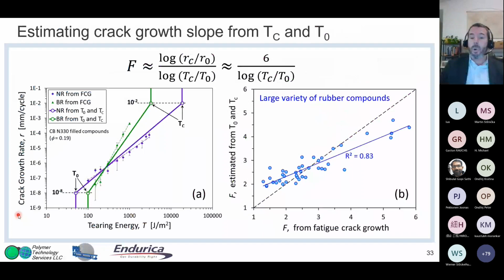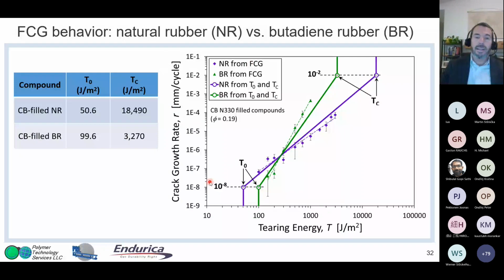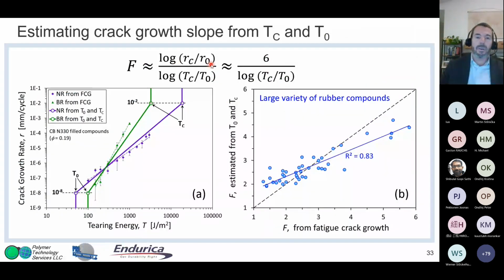So we showed that this actually works pretty well for a large variety of rubber compounds. If you get a crack growth slope F from fatigue crack growth testing, and then you get a value of F estimated from T0 and TC. Remember, I told you we can assume 6 decades, right? So here's 10 to the minus 2, here's 10 to the minus 8. That is 6 decades. So that's where that 6 comes from. It comes from RC over R0. And then if you take log of TC over T0 on the bottom, you can get a measure of F, right? It's just this over this. And when you fix the RC and R0, then all you need to know is TC and T0. And so, yeah, it works quite well.